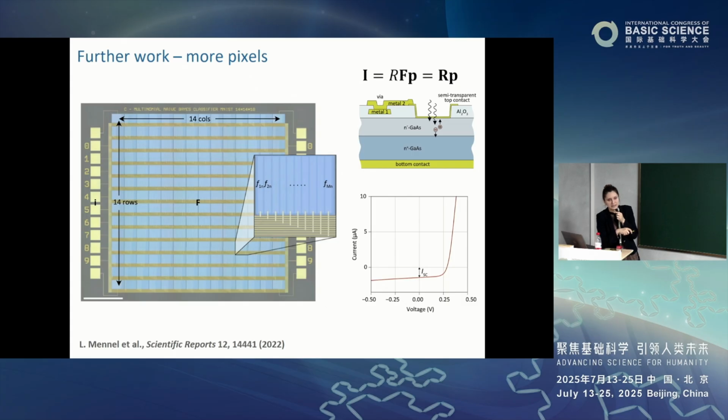The problem with 2D material is that, when I had to find a flake for the previous sensor, it was extremely big, like 100 microns. But usually people find flakes that are on the order of 10 microns. And if you have different flakes, there is a big chance they are not very uniform. So you have to come up with some other solution or grow perfect tungsten diselenide. Maybe somebody will be able to do it, with the same optical properties over big areas.